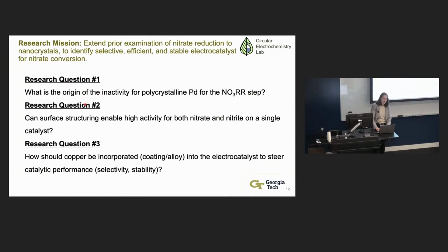And so what we've been looking at is how you can design these catalysts so that they can do these two steps in a way that can improve the rate of production, and what role surface structures play. When you buy materials from a distributor like Sigma Aldrich, most of the material will be in the most thermodynamically stable form, which is usually polycrystalline. Those will have different surface facets, and that all affects the binding of our reactants and intermediates. And then a third question that we've been looking at is, if you need to make bimetallics, what is the most efficient way for these bimetallics to be oriented so that you get the optimum properties of both the copper and the palladium. So coatings, alloys, and all of this has been what we've been looking at, with a focus on evaluating the selectivity and stability.